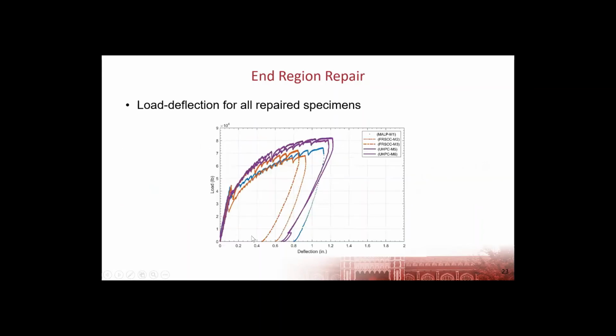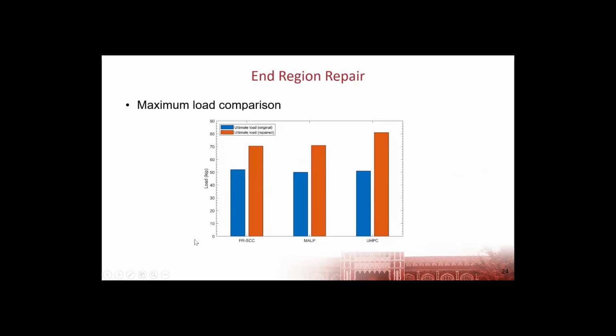If we look at the post-repair load test for all the specimens, we see very similar behavior early on. So very similar stiffness at the beginning of loading, and then the FR-SCC and the MALP concrete are very similar, where the UHPC gave us the highest load after repair. If we look just at maximum loads, for all specimens, we increased capacity by about 40% compared to the original non-strengthened case where we had that bond shear type failure.